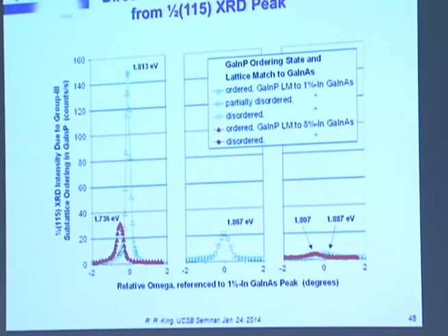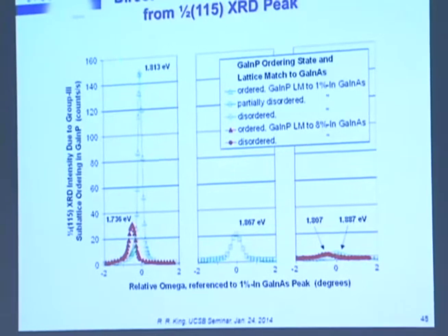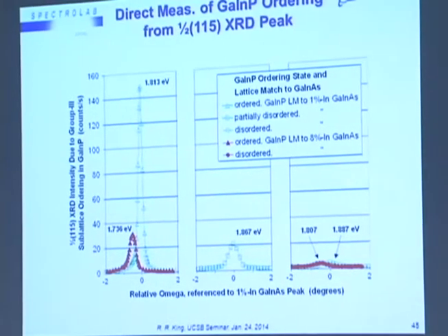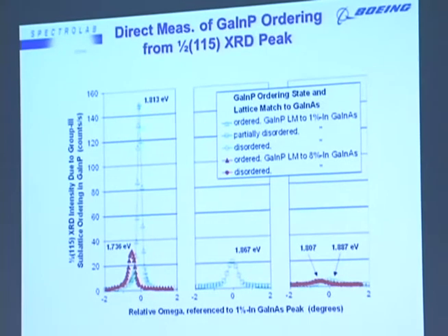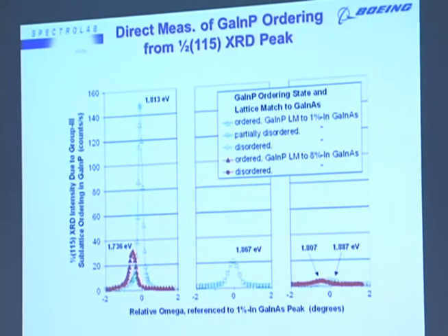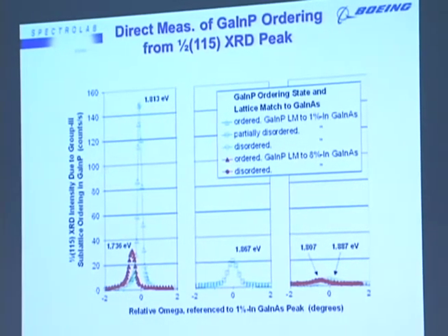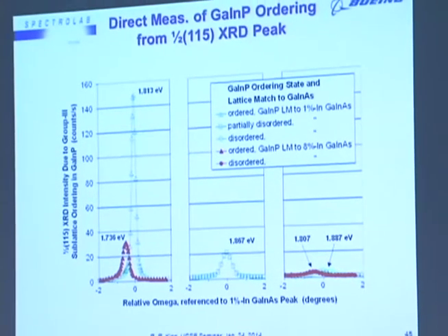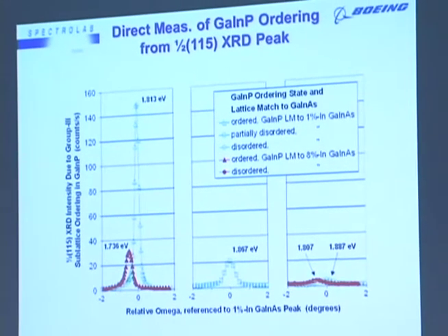We can measure this gallium indium phosphide ordering directly using the 1/2 115 X-ray diffraction peak. So for instance, this layer is largely ordered. We're able to see that peak coming from the 1/2 115 reflection, and this we see very little ordering. So this film is mostly disordered, and as a result, the band gap in this case goes from 1.81 to 1.89 eV.